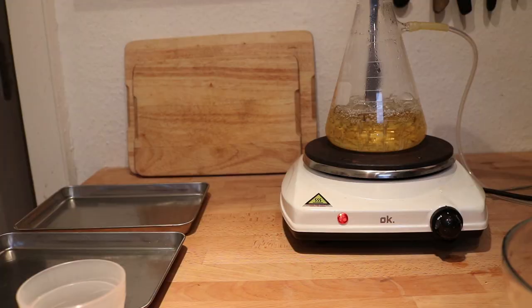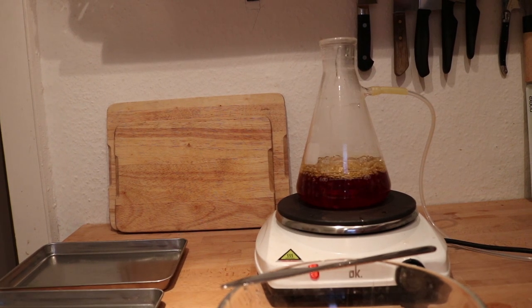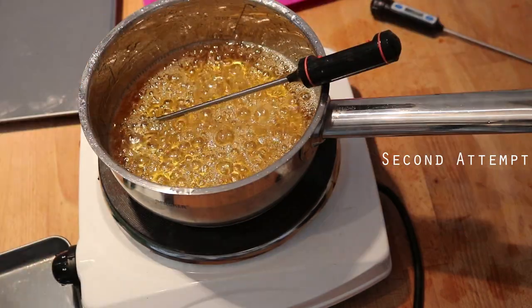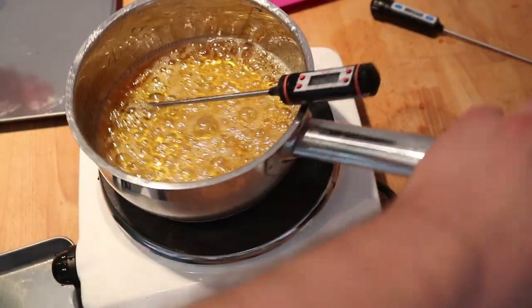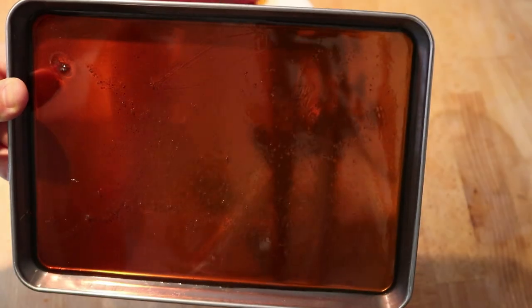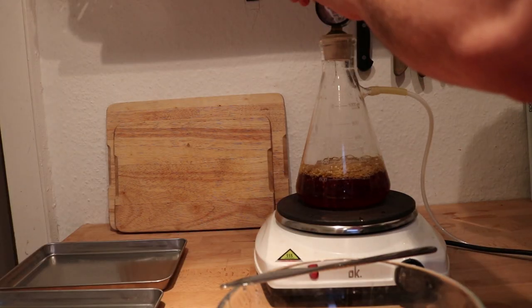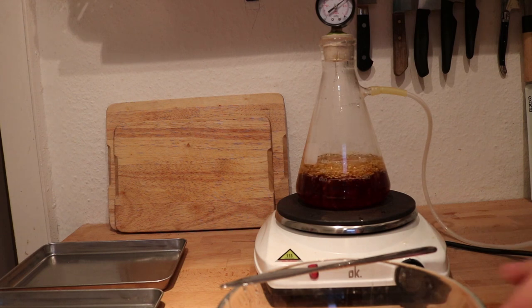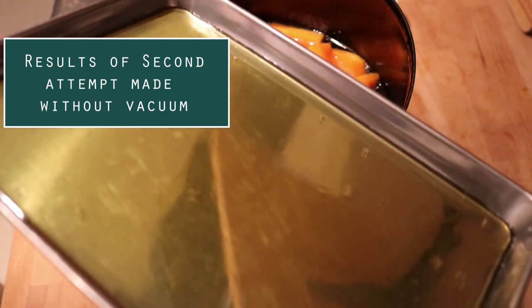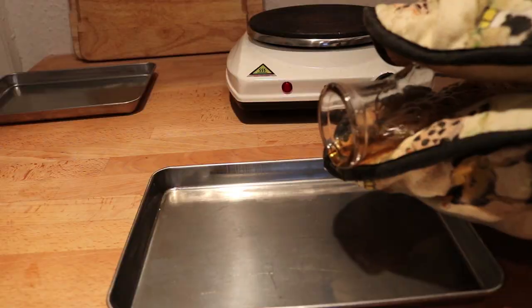Back to the sugar — you may notice that my sugar syrup is getting darker and darker, which is something I didn't really want. I actually ended up making two batches, playing around with the temperature to see if this was the problem. It seems as though this wasn't actually what was causing it — I suspect it has to do with the quality of sugar and corn syrup that I used. In essence, this shouldn't happen to you, but it still acts like glass and it kind of looks like beer glass, so I think it's probably still fine. Once my sugar was up to temperature, I plugged the cap and began pumping down to vacuum to remove the dissolved air from the syrup. It turned out to be practically pointless because in the second batch, not done in a vacuum flask, if you look at them both there really isn't much of a difference. Once the syrup was heated, you can pour it into your molds and let it cool completely.